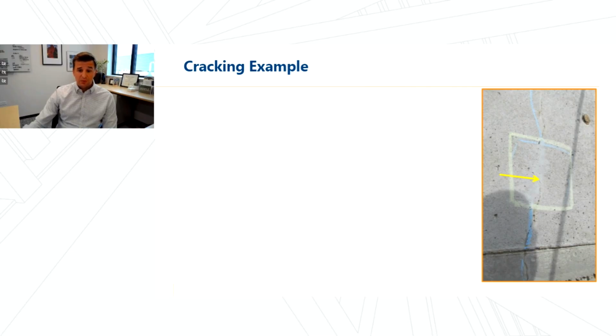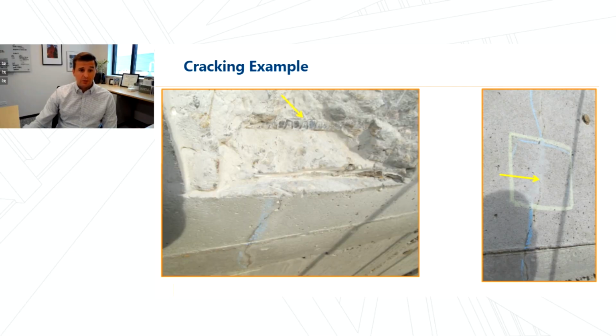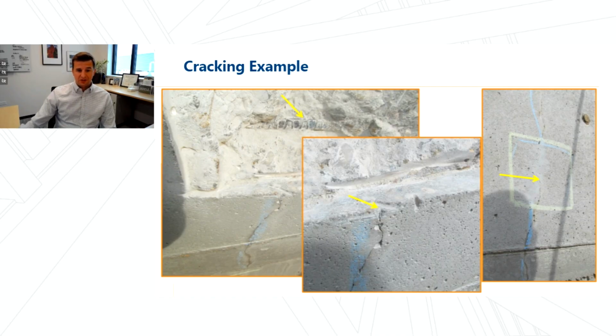This crack on the right, when we similarly make an inspection window, the first thing we notice is that there is not corroded reinforcement. The reinforcement that was revealed is uncorroded. Furthermore, the crack is only at the surface. It maybe extends a quarter inch, a few millimeters from the surface into the concrete. So we couple this observation with our understanding of structural behavior of this particular asset. We characterize that this is likely strain relief of flexural stresses from thermal effects. And so a crack of this nature does not need to be repaired, and that's an important finding.